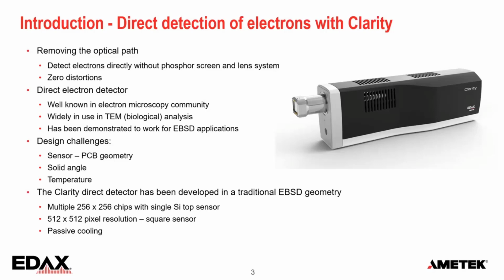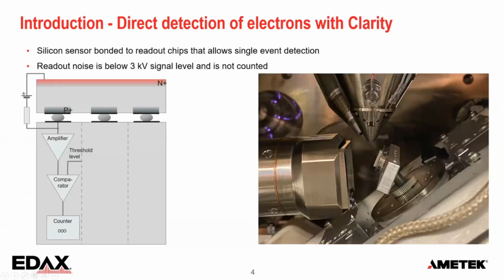Now, how does it work? Here we see the detector on the right-hand side and the chip itself is positioned very close to the sample. Sample is in a normal 70 degree EBSD position. And here on the left, you can see a little cross-section schematic of the sensor. And this is the top silicon sensor. So the electrons hit the sensor, there's a bias voltage, you get electron hole pairs, just like in an EDS detector actually.